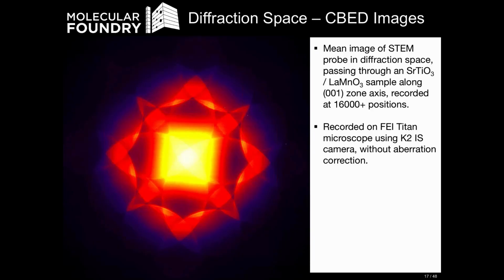If we perform a four-dimensional STEM experiment, this is the type of convergent beam electron diffraction image you get from the previous sample. This is the mean image of thousands of these STEM far-field diffraction patterns, recorded on the 001 zone axis, about 16,000 different images here. This was done on our uncorrected Titan microscope, using the K2IS camera. These patterns are what we're going to use to match to our simulations.